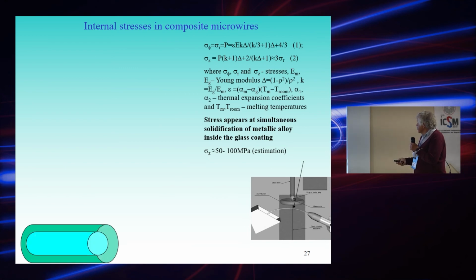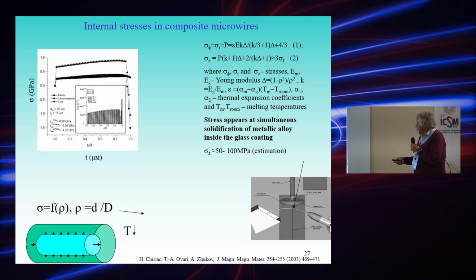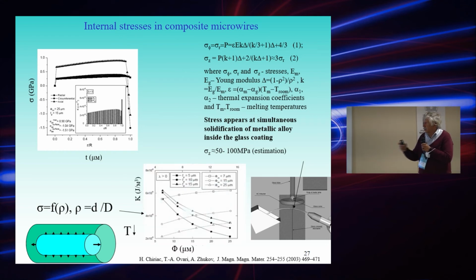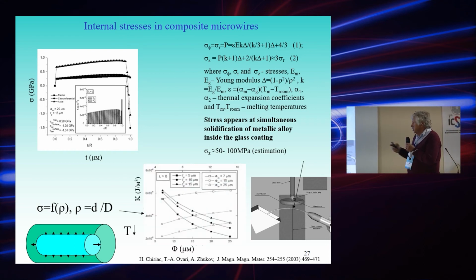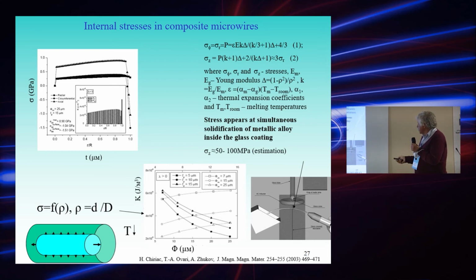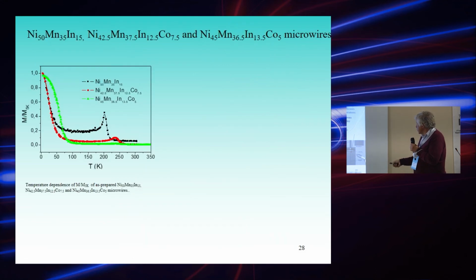And the problem should be related to the internal stresses, which are related to the fabrication technique. The origin comes from simultaneous cooling of glass and metal, and the metal has a much higher thermal expansion coefficient, and therefore axial stresses of almost half a gigapascal could be observed in most parts of these materials. In this way, we always study materials with strong internal stresses, initially in the axial direction, and we can even tune the strength of these internal stresses by changing the thickness of the glass coating, as shown in this picture.